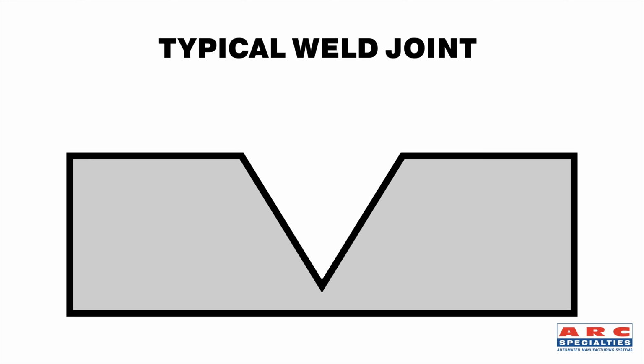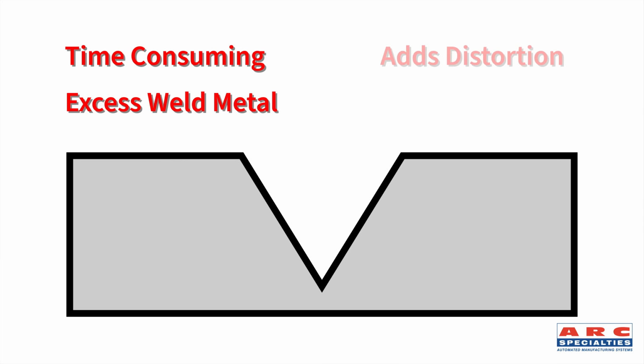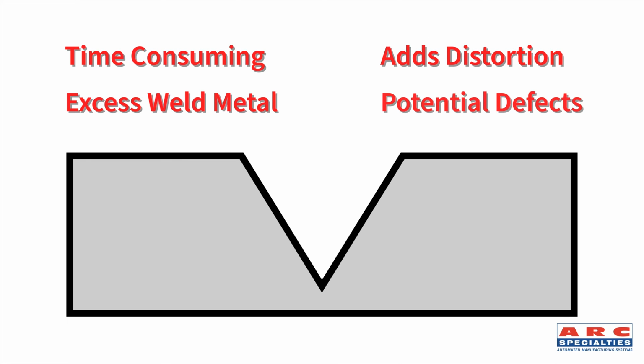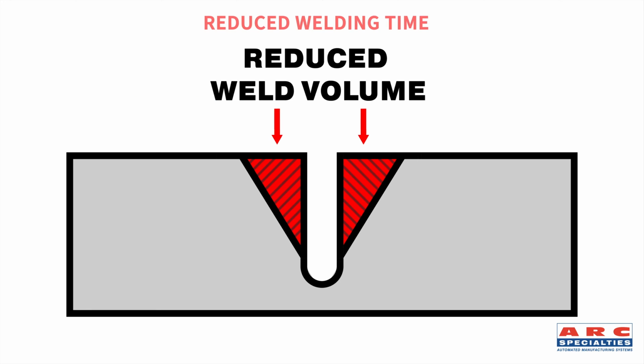not have to inspect. Most full penetration weld grooves incorporate a 75 degree included angle, and that creates a huge volume of weld metal. Wouldn't it be better to reduce this angle down close to zero? Now you're welding a square joint, and that's what we're going to talk about today.